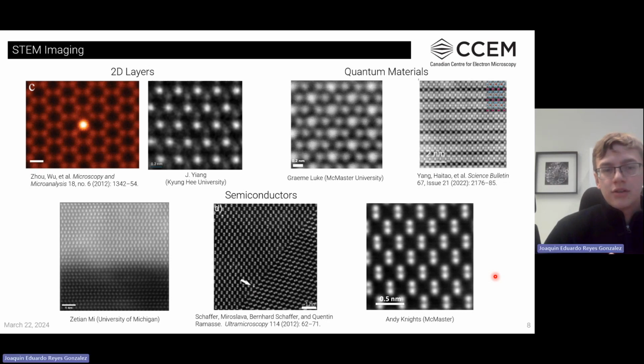So if you have the corrector giving you this very nice, very fine image, very well defined, that's already great. It's good to have that in a STEM. But the question is, why are we doing all of this STEM analysis at the low KVs if we have something such as an instrument that can give us fantastic images at 300 KVs in other scopes, or fantastic images at 200 KVs in other scopes, because we can get slightly better resolution in those.